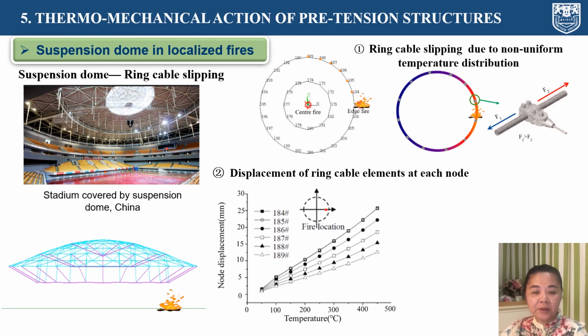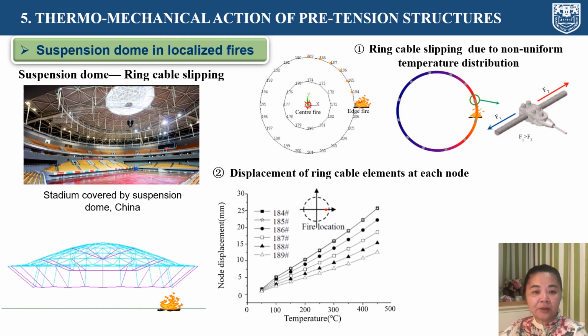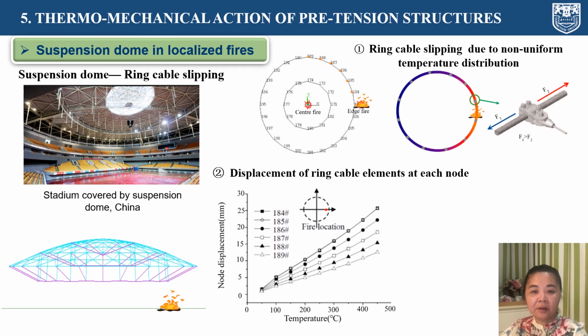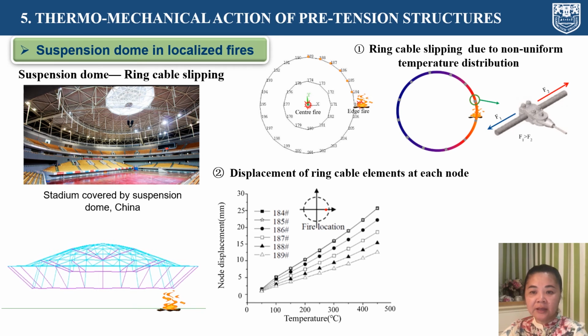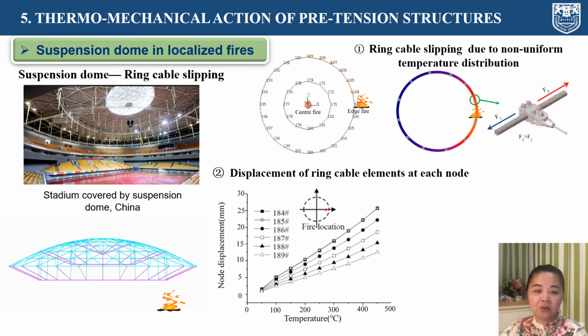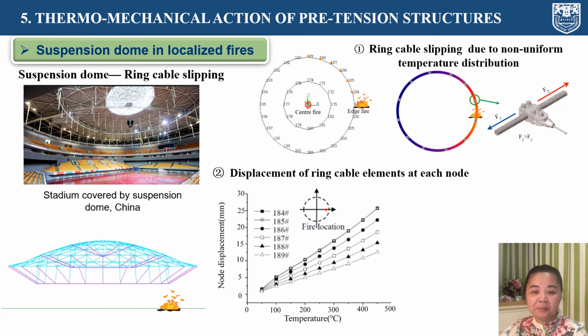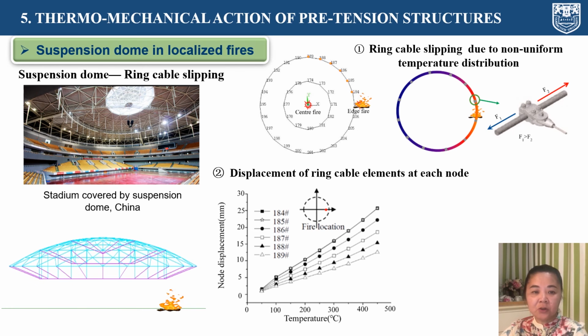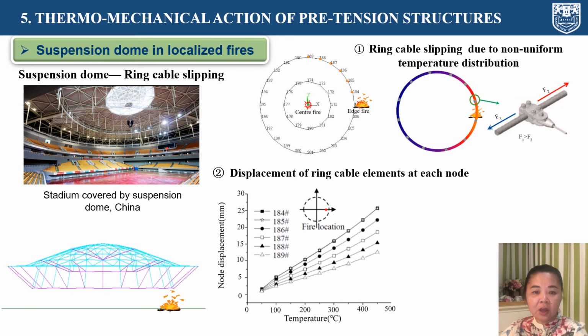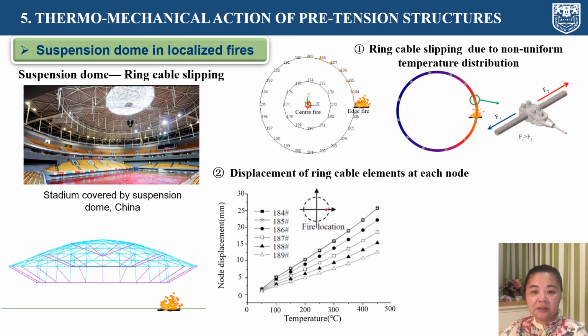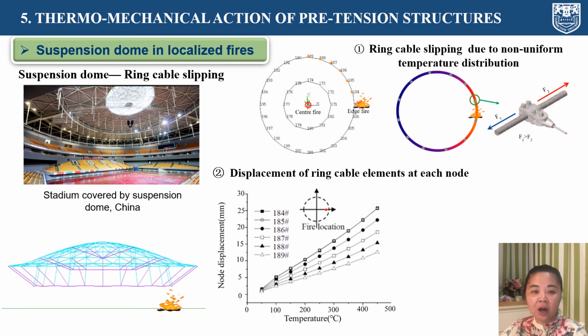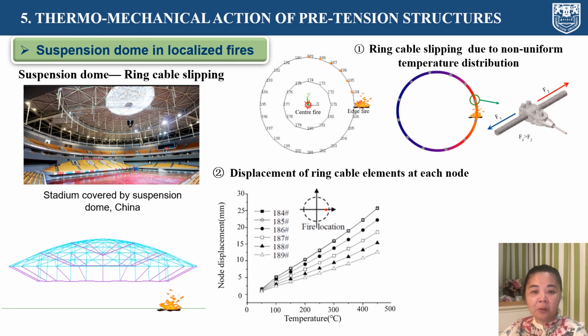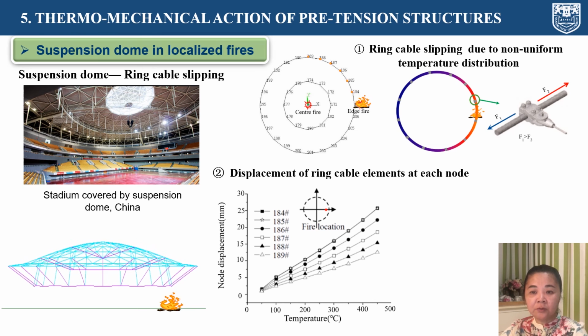A suspension dome is formed by the upper single-layer dome and the lower pretensioned cable-strut system. The pretensioned ring cables enhance the stiffness of the structure. It is worth noting that, as a suspension dome is subject to localized fire, the non-uniform temperature distribution along the pretensioned ring cable is unbalanced due to different thermal expansion.